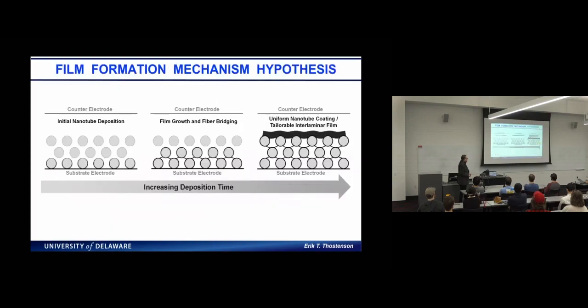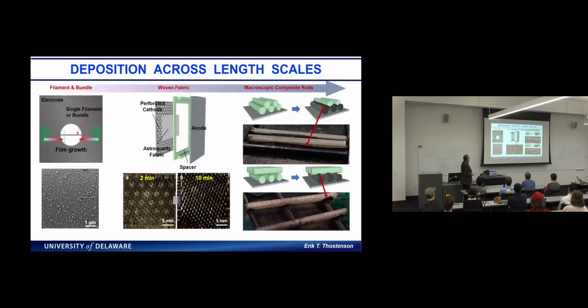And then I think what's really unique about this is, as I mentioned, the tubes don't just rain down onto the surface, but they deposit on the back electrode. So if we have a substrate electrode, the carbon nanotubes want to actually get to that electrode. And of course, what happens is we get electrolysis of water. It's like the high school experiment where you split oxygen and hydrogen, right? So that electrolysis changes the pH, and then that causes the tubes to precipitate out. And so because it's electrically conductive, it grows as an extension of this electrode. And we've studied a lot of the kinetics of that deposition.